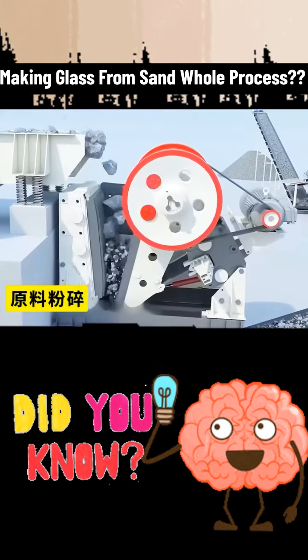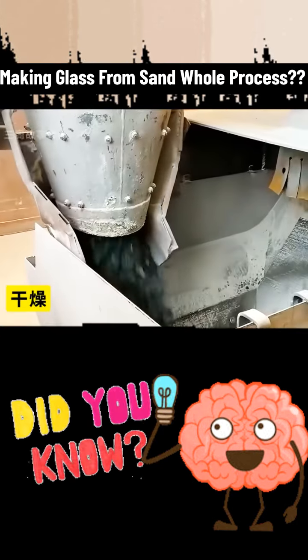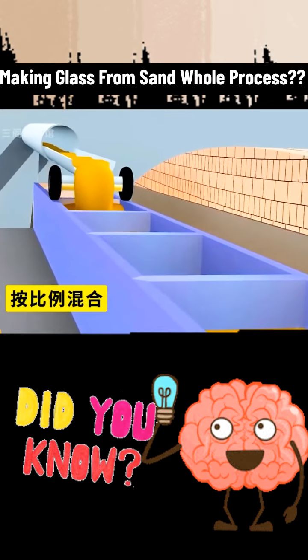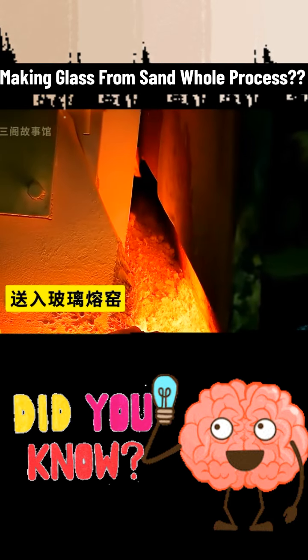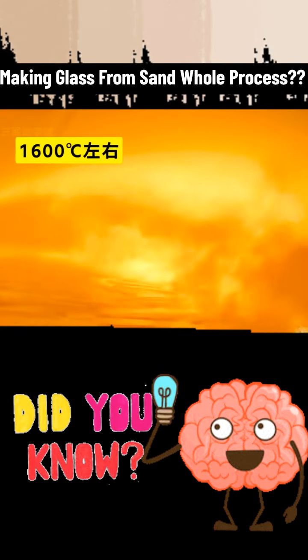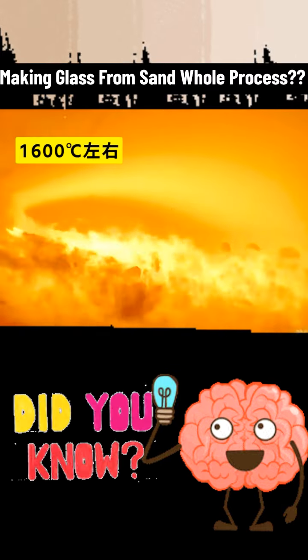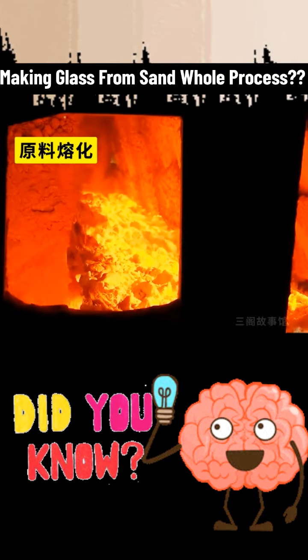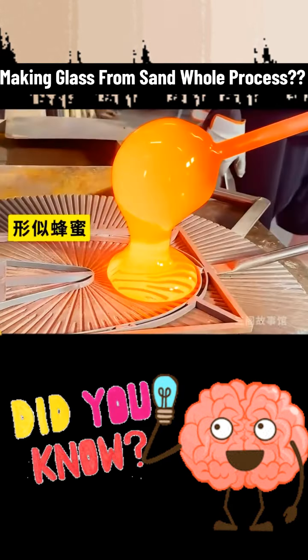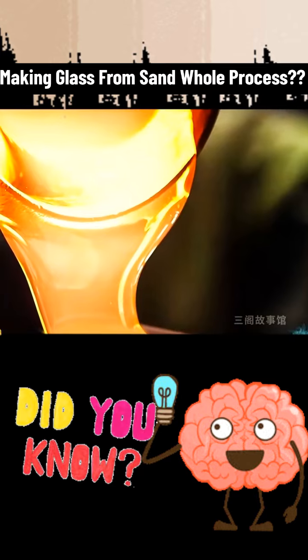Before manufacturing, the sand undergoes crushing, screening, and drying to boost purity. It's then weighed and mixed proportionately. These mixed materials are fed into a melting furnace, where alternating flames elevate the temperature to around 1600 degrees. At this heat, the materials gradually melt and chemically react, forming a honey-like viscous glass liquid.